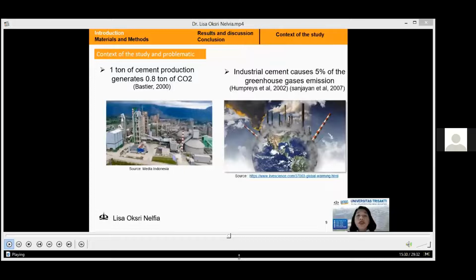On the other hand, the use of cement in building construction or other infrastructure works creates a negative impact on the environment. The literature revealed that each ton of cement production generates nearly 0.8 tons of carbon dioxide, which is released into the atmosphere. It's caused by using a large amount of energy and a high temperature of approximately 1450 degrees Celsius to produce the clinker, which is the main component of cement. Hence, the cement industry causes 5% of greenhouse gas emissions.